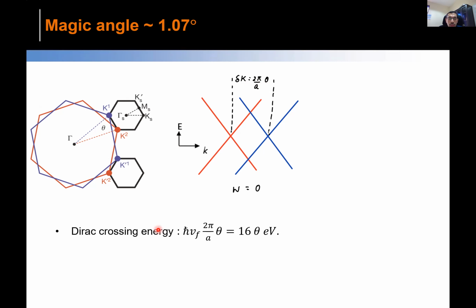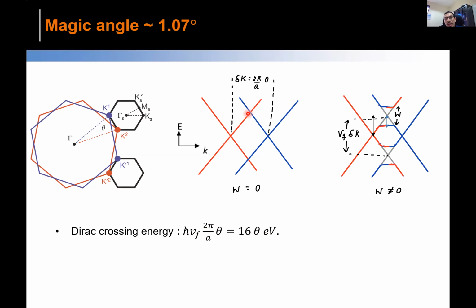So far so good. For the Dirac crossing point in energy, we know that the relation for graphene is a linear dispersion, so energy is proportional to momentum. So the energy separation between these two crossing points is nothing but h-bar times the Fermi velocity times 2 pi by a times theta, which is about 16 theta in eV. Now, this physics is what I said if there is no tunneling, no interaction and no hybridization between the layers. But indeed, in real physics, we know that once you do this, there will be tunneling between the top and bottom graphene, right?